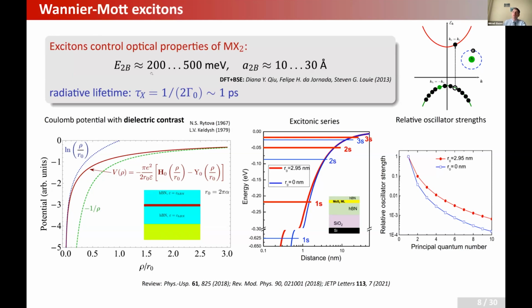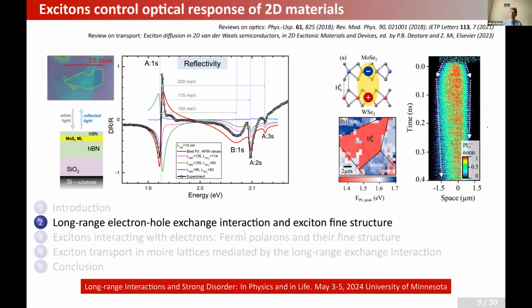Depending on the surroundings and the particular material, you can have excitons with rather large binding energies, hundreds of milli-electron volts, and rather small Bohr radii. Still, these are large radius excitons in comparison with the lattice size. They cover at least several tens, up to 100 unit cells. They also have relatively short radiative lifetime and relatively strong coupling to light, again because the Coulomb interaction is rather strong. I will not go into any details about the interesting physics related to the excitonic series, nor about the control of excitonic properties in these van der Waals heterostructures.